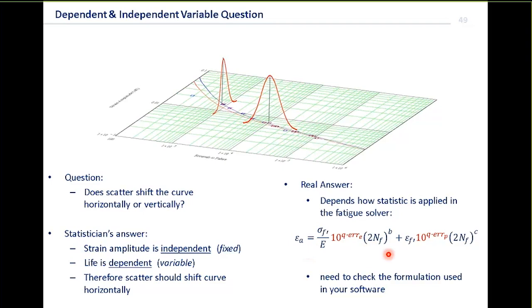But whether you're moving it up and down or left and right really doesn't matter, providing you're consistent in the way you're measuring your statistics. So if you're using your own software to do this, make sure that if you're putting it into our software, in stress life SN, the curve moves horizontally, so your standard error value will come from your cycles to failure. But in EN, your standard error value comes from the strain, the elastic strain or the plastic strain that we're using. If you've still got more questions on that, then we can talk about those when we're finished.